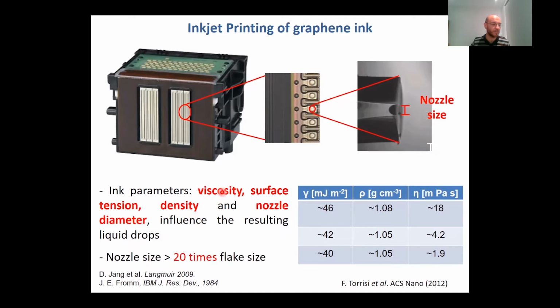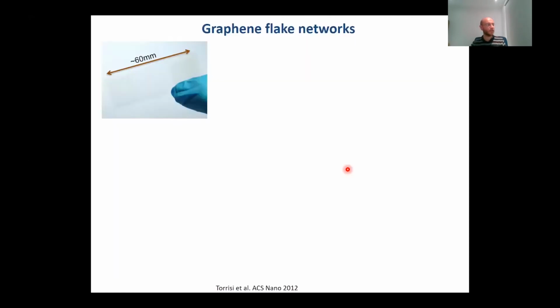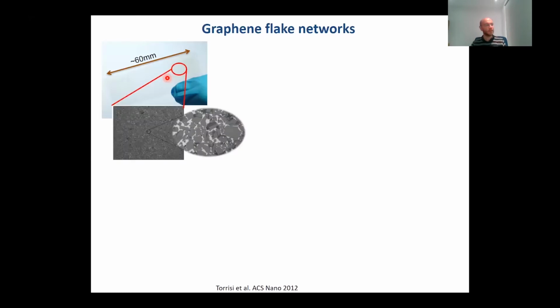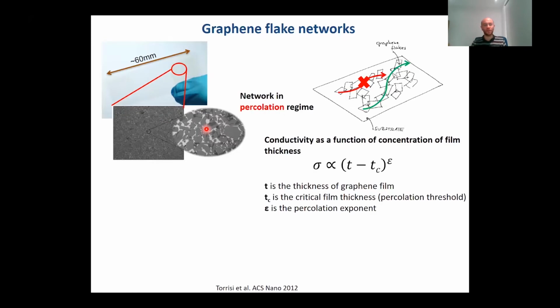And then there is strong work on the tunability of viscosity, surface tension, and density of this material so that you can get so-called drop on demand. For example, we optimized printing techniques to make sure that we have single drop ejection from a nozzle. So this is, for example, an optimized inkjet printed graphene ink. And if you get drop on demand, you can control the volume. By controlling the volume, you can even get very nice and thin films that can work as transparent conductors. So if we investigate what these look like, they really look like networks of large flakes. And of course, in this case, percolation rules.